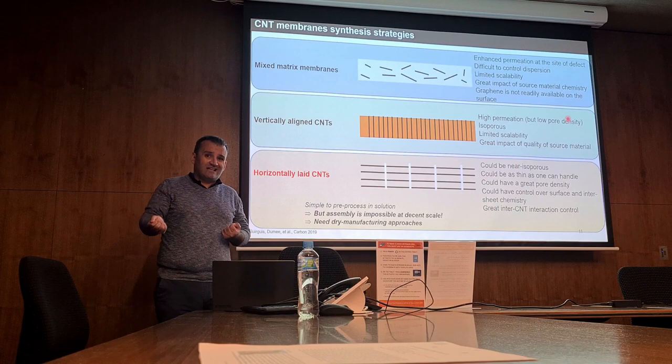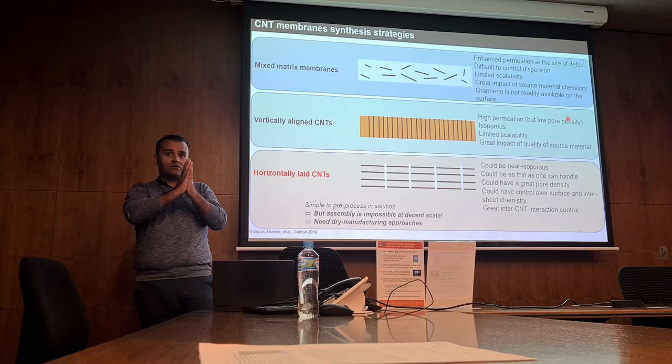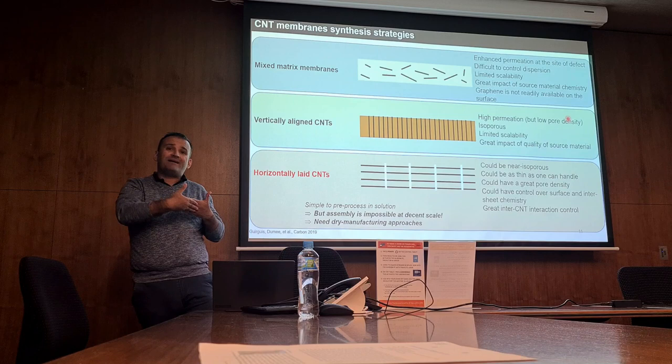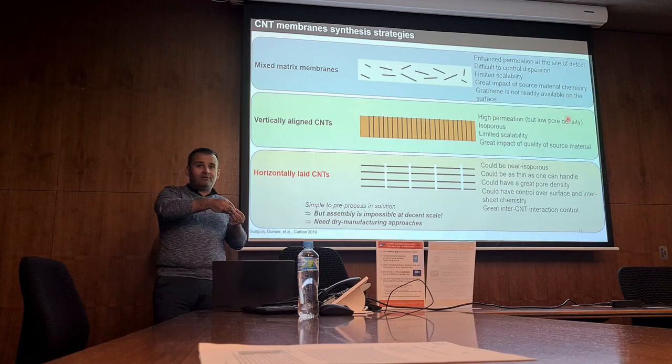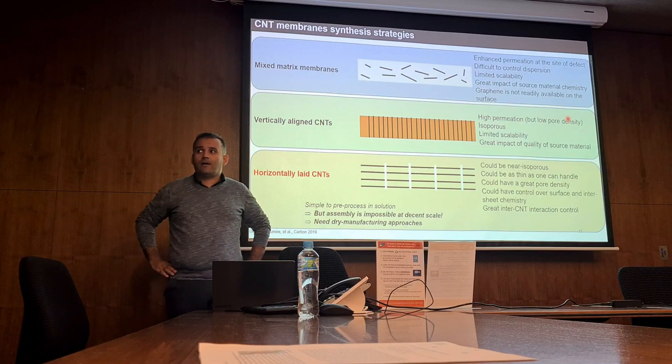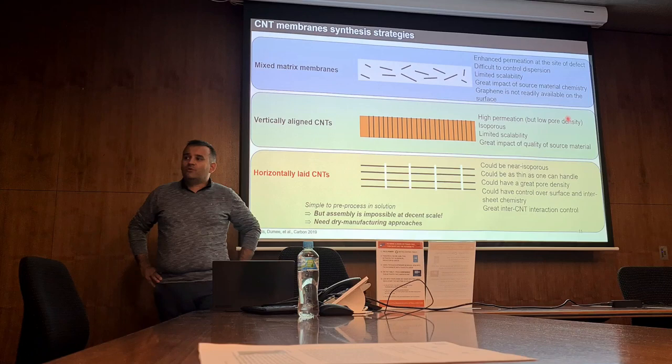Meaning you can grow the CNTs as vertical tubes on a silicon wafer, pull the edge and it comes as a web. The way it works is that you have to control the size of the catalyst on the surface of the wafer in order to have a high pattern density of tubes, and you generate nanofibrils of carbon between the tubes. But when you pull the CNTs, they all come together sheet by sheet. So very nice technology, very advanced in terms of growth and synthesis by chemical vapor deposition. But CSIRO and UTexas mastered this, and now I think 4 companies have spun from this technology.